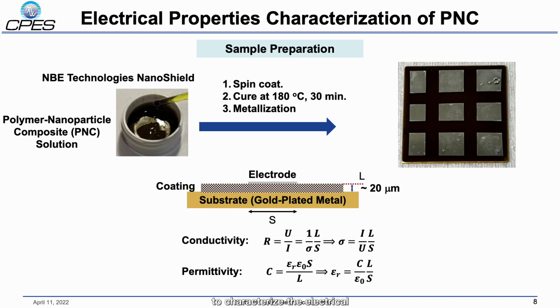To characterize the electrical properties of this material, we made a few thin film samples. So this picture shows the Polymer-Nanoparticle Composite solution. I will just call it PNC later. The material is received from NBE technology. To make this thin film sample, we use the spin coating process. First, we spin coat the solution on the gold-plated metal substrate, and then we cure it at 180 degrees C for 30 minutes to form this thin film coating.